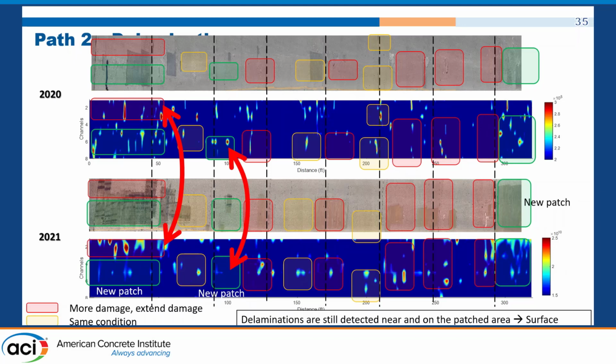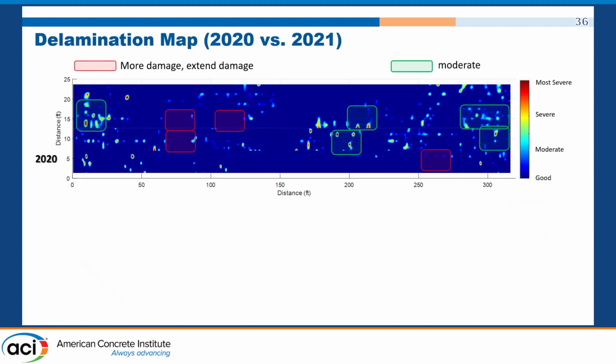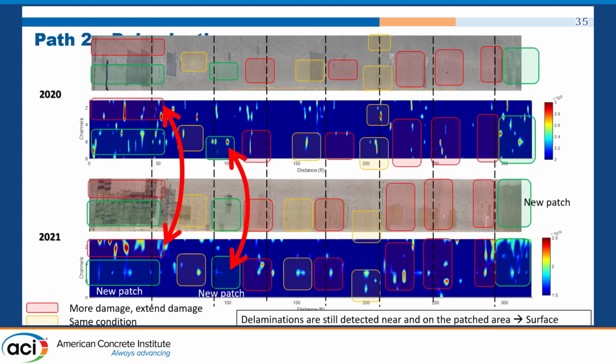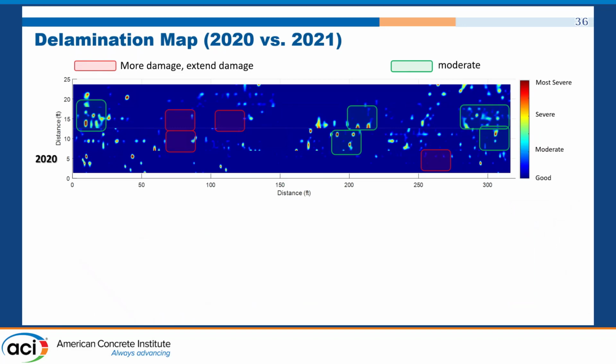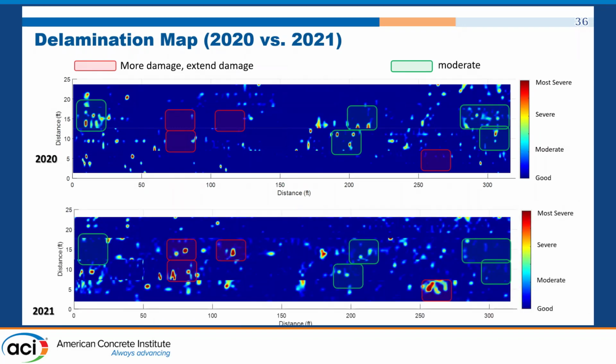So maybe we have to look at here, maybe we need cathodic protection or a sacrificial anode, or we can do a different way. But after the patch, there is a lot of even worse damage in here. So this is a kind of good opportunity. Actually, we validate, and we're also looking at the quality of the repair that we do, of course, and then we can see the entire bridge.